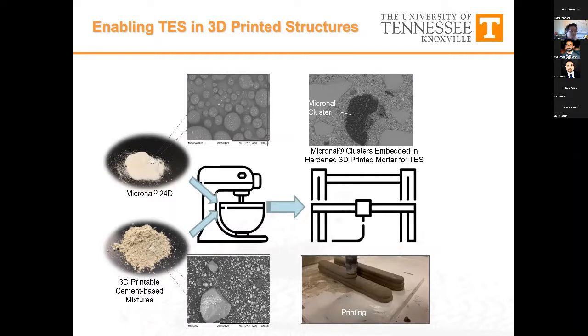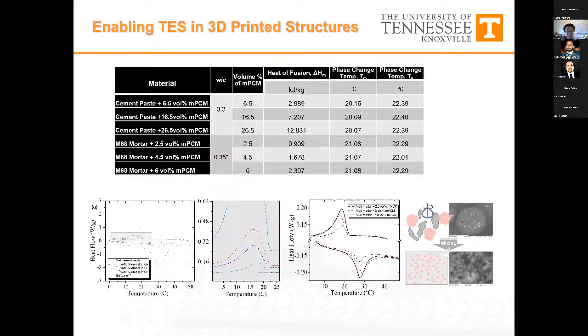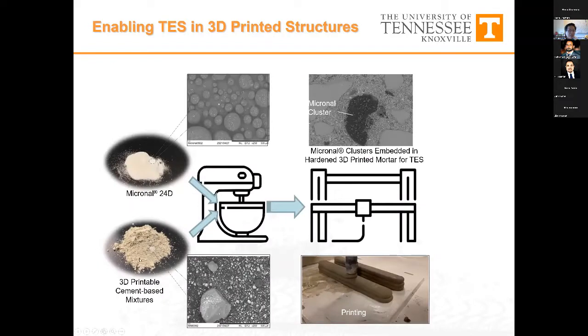And once again, this is a very well understood commercially available PCM system, and we want to add that directly into a 3D printable cementitious mixture. This is the easiest approach for practitioners: if we want to invoke certain functionalities, we simply put the functional additives in and add water into the premix, and that's good to go. So this is the first approach that we take.